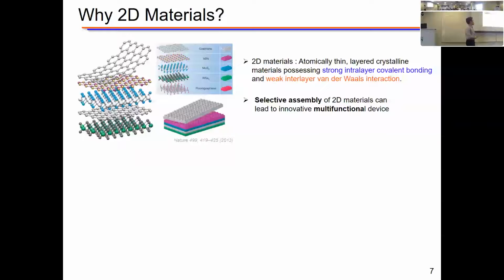To give you a brief description, 2D materials are atomically thin, layered crystalline materials held with strong in-plane covalent bonds and held by weak interlayer van der Waals interaction. And on the left, I'm showing you one of the popular descriptions of 2D materials as a Lego block. So what that means is we can selectively assemble various combinations of 2D materials such as semi-metallic graphene, insulating hexagonal boron nitride, or semiconducting transition metal dichalcogenides such as molybdenum selenide. By doing so, we can create innovative multifunctional devices.